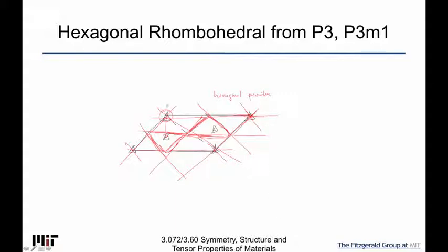And the sixfold is a bit more obvious because, of course, in the sixfold, I have sixfold in the corner. And the internal guys here are threefold, so I have no option. So same thing, I can only go up. So hexagonal primitive or the hexagonal rhombohedral. And that is what we get from our hexagonal bases if we were to look at the lattices that generate.